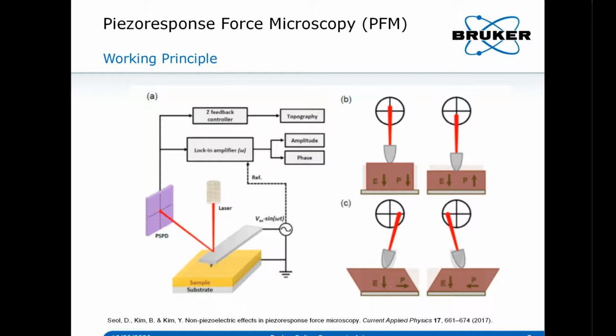So in order to make this kind of mechanical response stronger or easier to detect, we can use different approaches. The first one, and the most common one, is that we apply AC instead of DC signals. Under this AC electric field, the mechanical deformation of the materials also follows these AC patterns. And from this AC signal, we can use the lock-in amplifier to extract and demodulate. From the amplitude and phase, we can know the piezo response strength and the piezo response orientation, or the piezo grain orientation, or the polarization direction, depending on what kind of material you're talking about. So this is the basic working principle of the PFM.